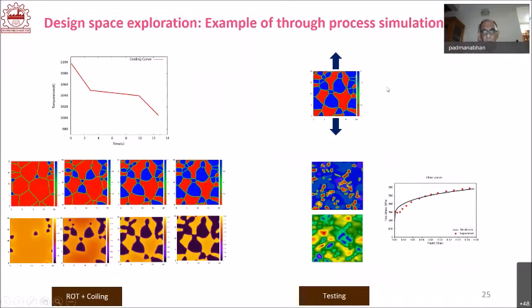For example, for the whole process, supposing I want to understand the runout table and coiling. So I concentrate on this. It starts with this, and by the time I come to the lowest temperature here, the microstructure would have developed this. And here again, one thing you have to remember, this is ferrite and martensite. So the dark ones are the martensite. And here you see the ferrite, the grain boundaries are not shown. This is because of the finite element analysis which is used.